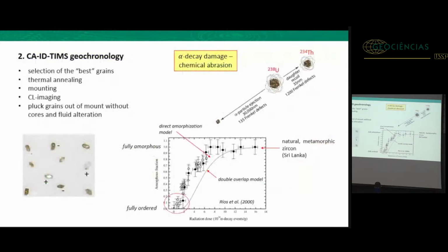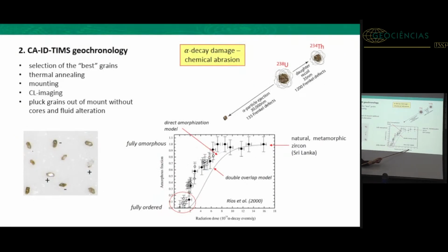But sometimes you're also not successful. So what we will try, we can define two thresholds. So one is about 2.5 times 10 to the 18 alpha decays per gram, which is called the first percolation point. And the second one is at about 8 times 10 to the 18 alpha decays per gram. So here, these zircons we can still repair. We do a treatment, annealing, to repair the intact part of the grain, and we dissolve the more damaged part of the grain. And this is called chemical abrasion.